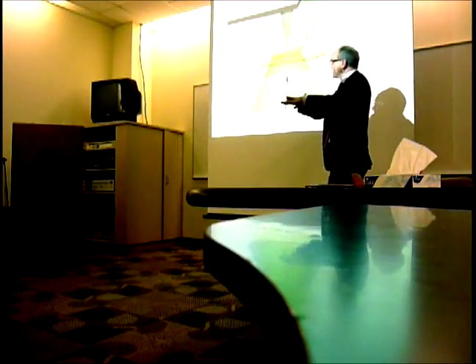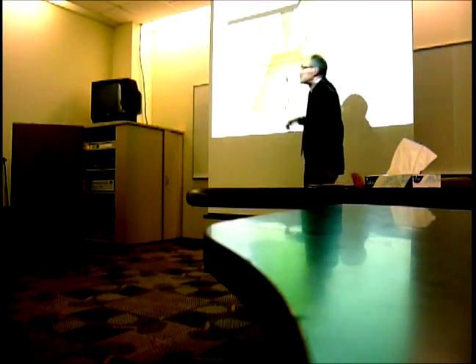And I first want to introduce you to a reaction. You don't have to remember very well what it is. The most important thing to remember is that this molecule has an NO2 at the end. And then here, what you do is you couple it, and then you make this kind of functionality. So what is the experiment all about? The experiment is as follows. We put this molecule with its NO2 on a gold plate with its sulfur groups, thiol groups.